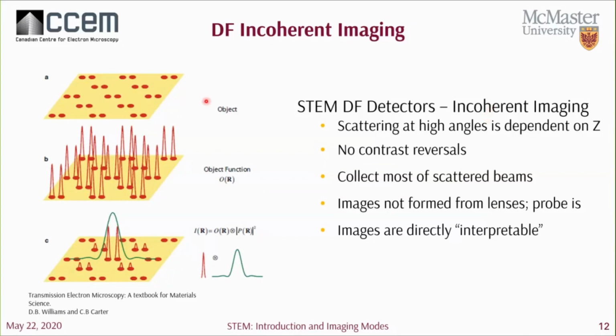So here, if we just consider a layer of atoms, we can plot the object function, which describes the potential or the probabilities for each of these atoms to scatter electrons at high angles, i.e. the scattering cross sections. And these peak heights are approximately proportional to a little less than Z squared. So the sharpness in the peaks here indicates that each atom is an independent scatterer.